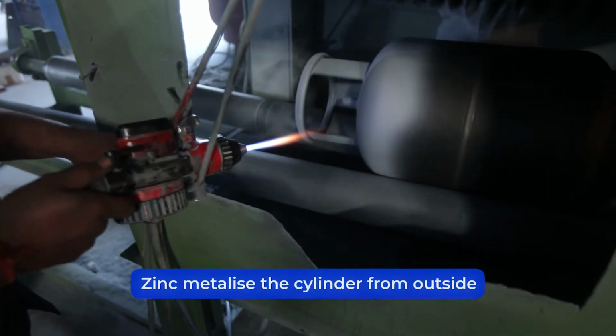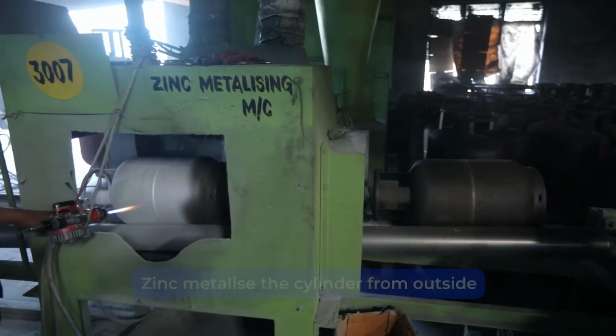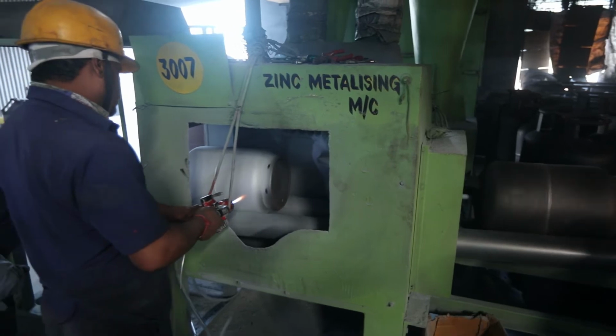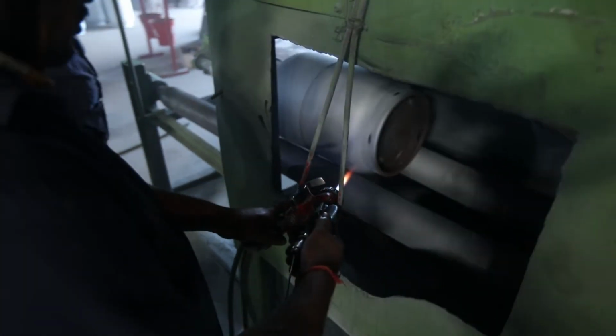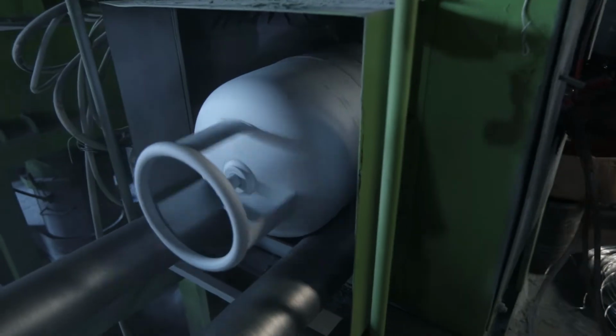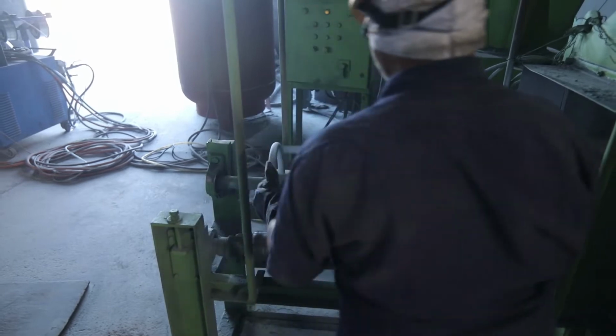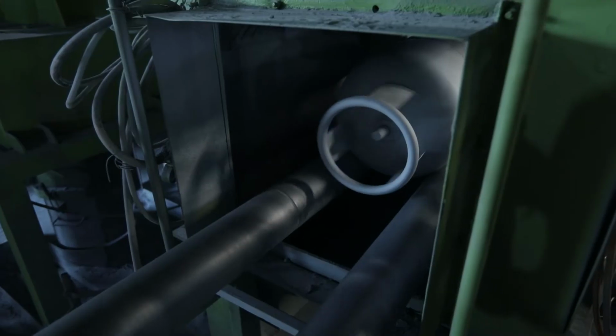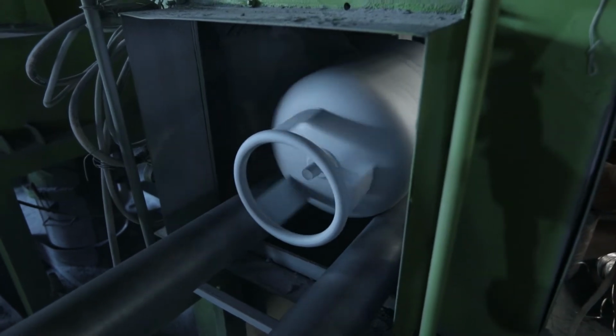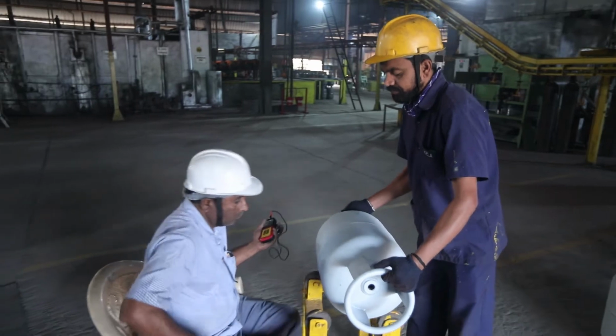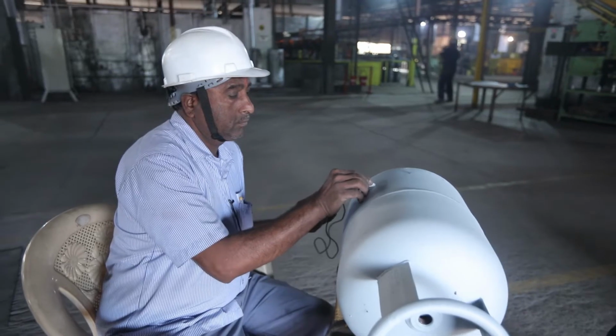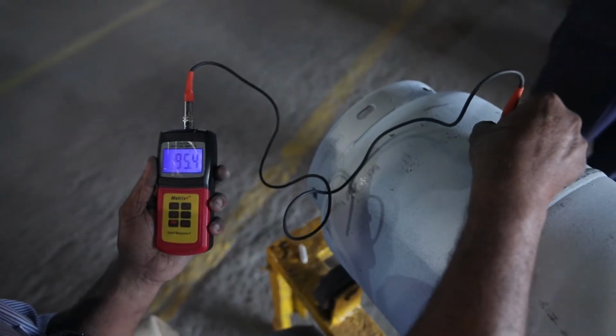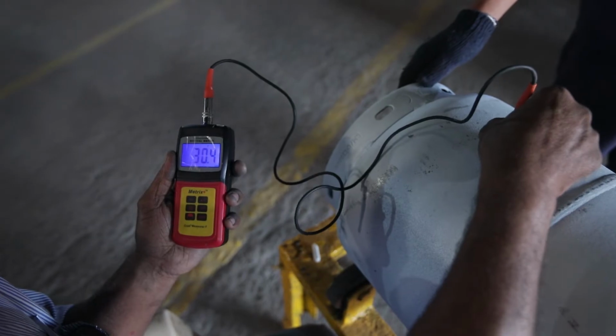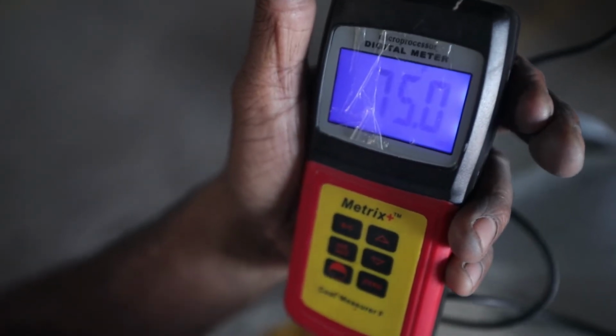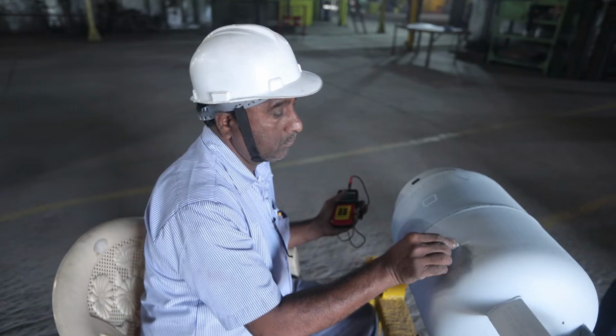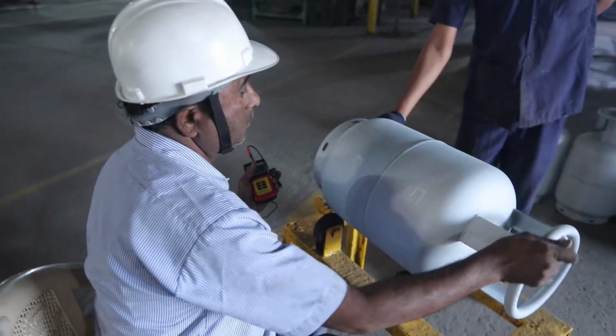A zinc metallizing operation is carried out as per the specification to protect the surface of the cylinder from corrosion. The operation includes zinc wire spray metallizing by a metallizing gun. To obtain metallizing thickness of minimum 40 micron on cylinder surface, rotational time of cylinder and wire melting speed is controlled. To melt zinc wire, a mixture of oxygen gas and LPG gas is used. And for feeding the zinc wire in a metallizing gun, air pressure is used. In this process, a zinc wire of 3.15 mm diameter of IS 12447 standard is used.